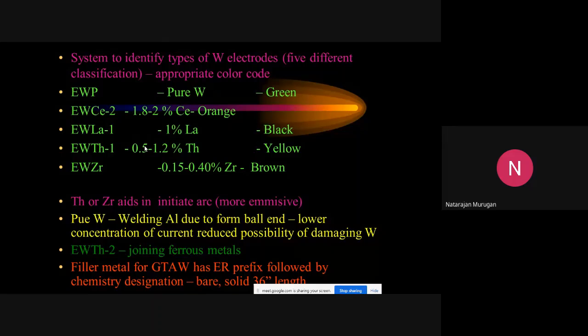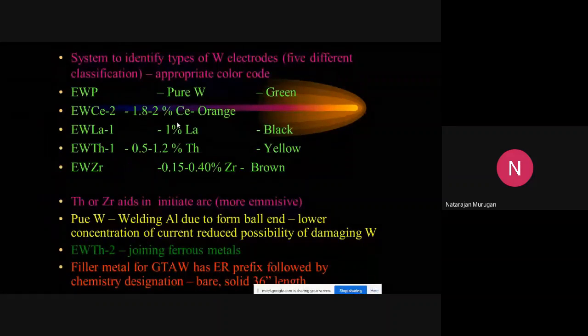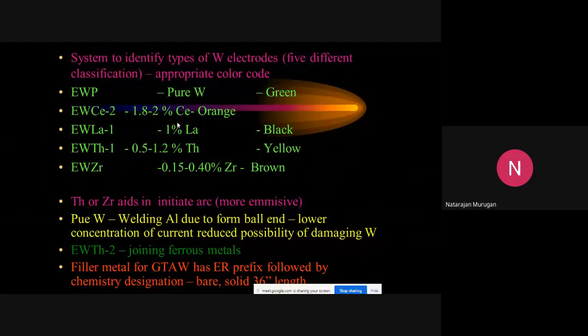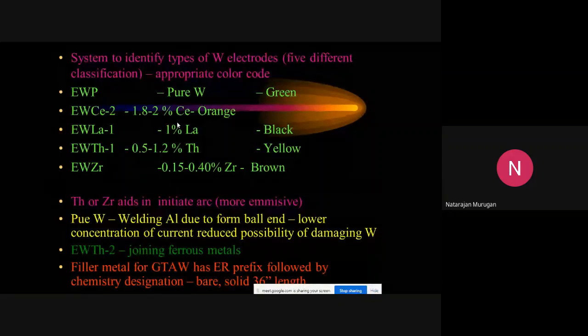Okay, TIG process, it's a very good process, very efficient. You can have good quality, right? So these are the different types, and they are color coded: orange, green, black, yellow. Thorium is added. These alloying elements are added to quickly initiate the arc and maintain the arc. Thorium is nowadays not recommended because of radiation. So thorium and zirconium aid in initiating the arc. Pure tungsten is mainly used in aluminum welding.